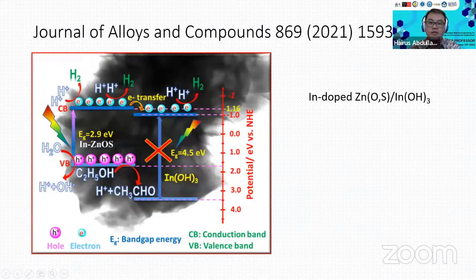Okay, and then here we try another concept with the indium doped ZnOS. I do not show the characterization, but I think this is quite interesting to show you, because indium hydroxide actually has a very wide band gap and is not active during the reaction. Right? You see in the figure the band gap is around 4.5. So basically, if we use visible light, this material is not active. However, when we dope the ZnOS with indium, the band gap becomes smaller. Then we have the photoexcited electron.